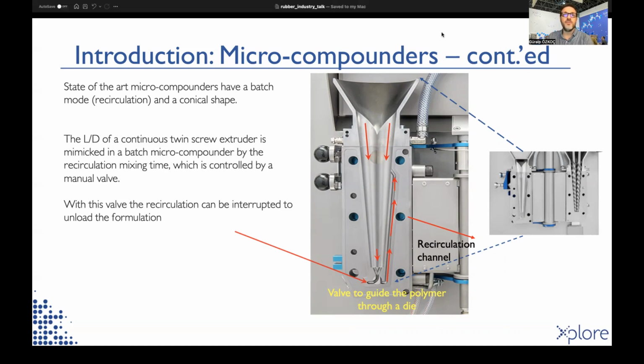Here, there's a valve that guides the melt through the recirculation channel to the top, and the melt is again entered into the shear zone. And in this way, the mixing can be sustained. The number of the pass is defined by the time that you keep the valve closed. Once you open the valve, the melt flows out. In a parallel twin screw extruder, the residence time is controlled by L/D ratio of the screw and the screw geometry. Here, it's controlled by the time.